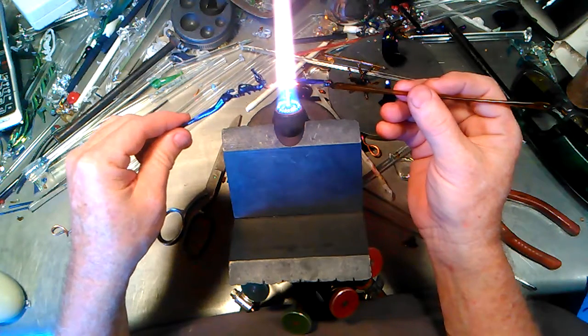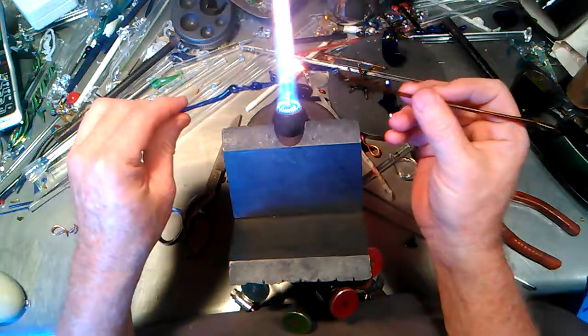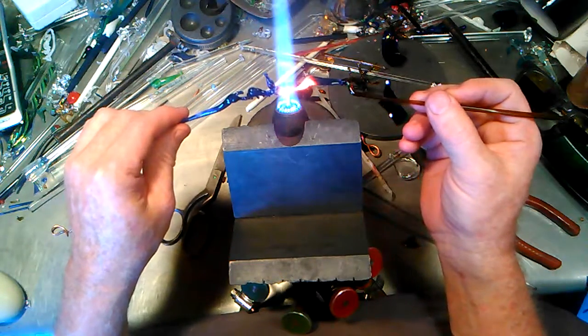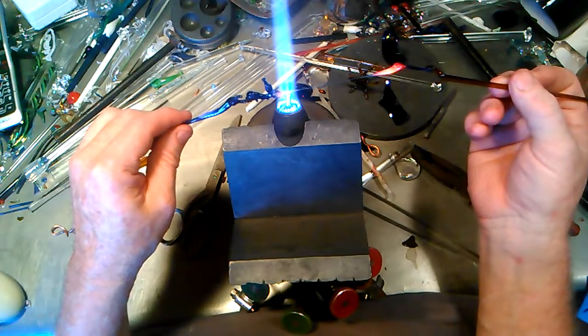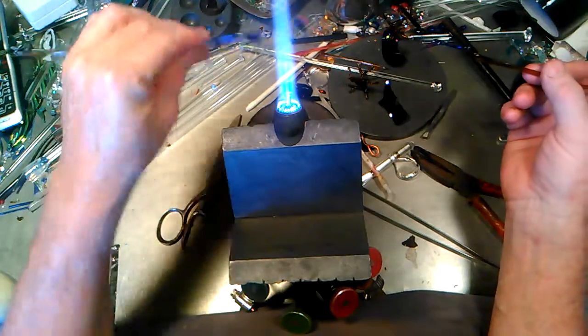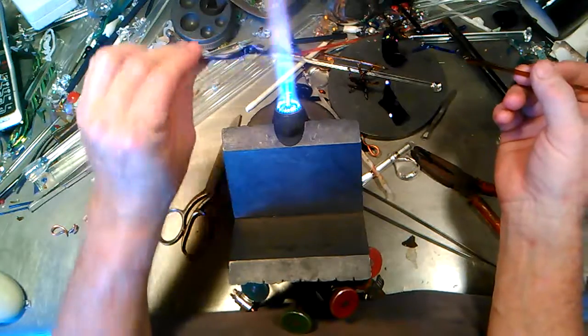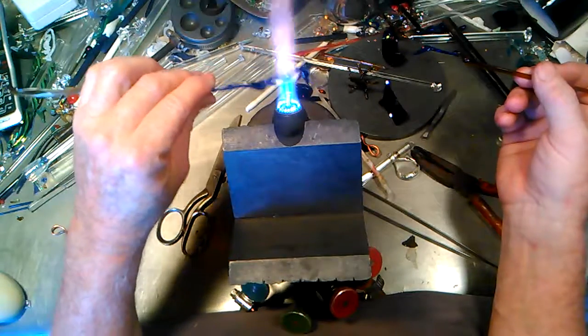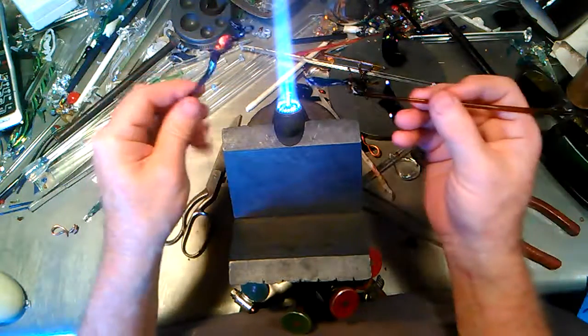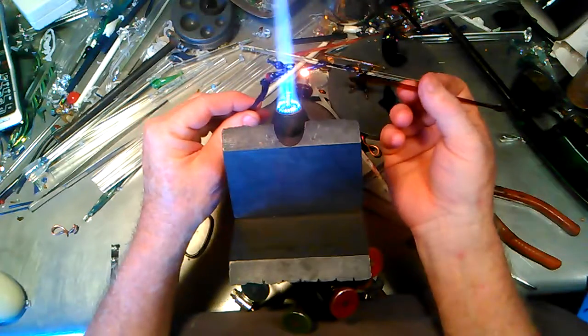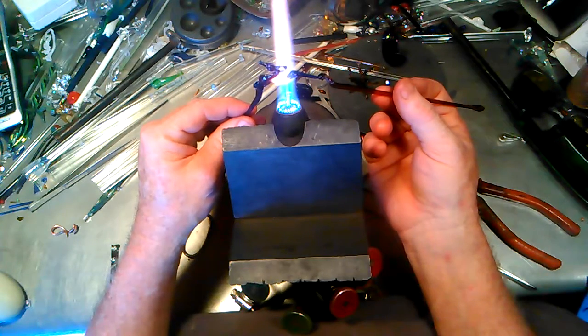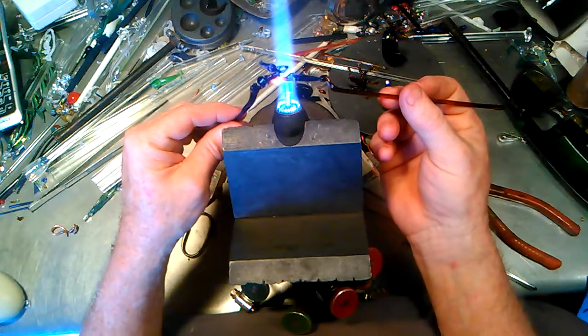Now, the quality of this blue glass is already causing problems and devitrification, which means that it's wrinkling on the surface. I'm going to try to fire polish some of it out. But with not knowing where the glass comes from doesn't help. I mean, I know where it came from, but not working with this type of glass before doesn't help. I just know a little bit of the nature of the beast. I know approximately what I can get away with. And if you know some of the parameters and factors of your work, I mean your material, that helps.